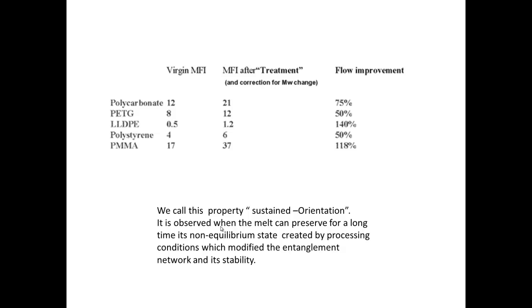There are some collateral effects if I work at high temperature. This is inherent to plastics. If you treat plastic in a twin screw or a single screw, there is a certain loss of molecular weight, which is inherent to processing it at high temperature. So if there is any molecular weight change, I need to take that into account when I calculate the flow improvement, because, as we know, the molecular weight also has an influence on the viscosity.